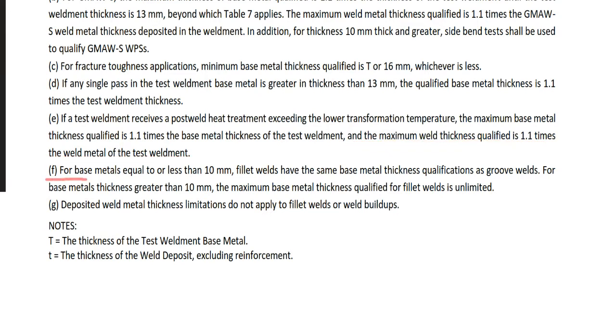F. For base metal equal to or less than 10 millimeter, fillet welds have the same base metal thickness qualification as groove welds. Base metal is less than or equal to 10 millimeter. Fillet welds have the same base metal thickness. So if this is 9 or 10 millimeter, then the fillet weld is also qualified by this groove weld base metal thickness qualification. And this qualification can qualify this fillet weld.